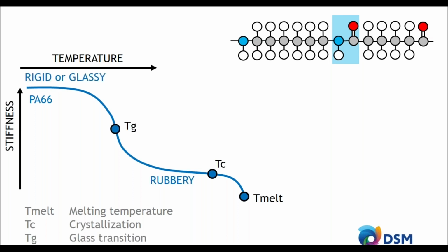And the third point is also very important, called the glass transition temperature. This glass transition temperature represents a large step in the performance of your material. Above the glass transition temperature, you have a more rubbery state, and below it a very rigid, glassy state. The glass transition temperature of a polyamide 6,6 is around 70 degrees C.